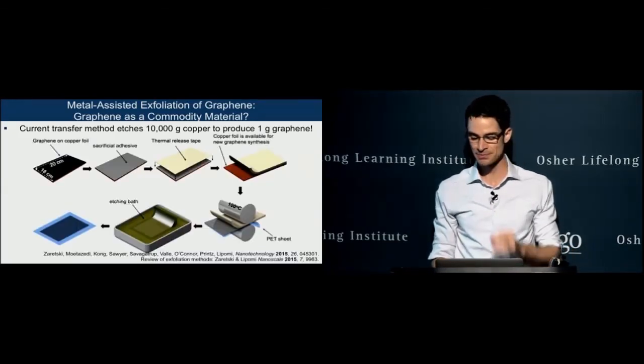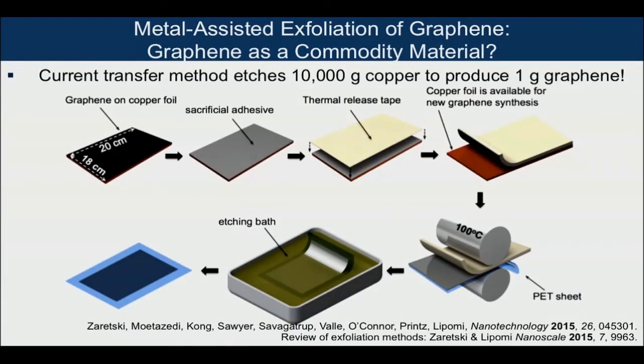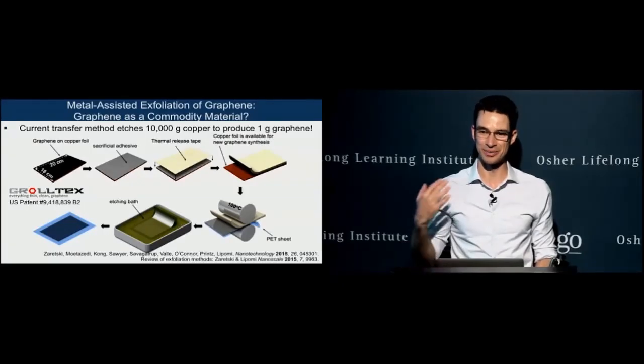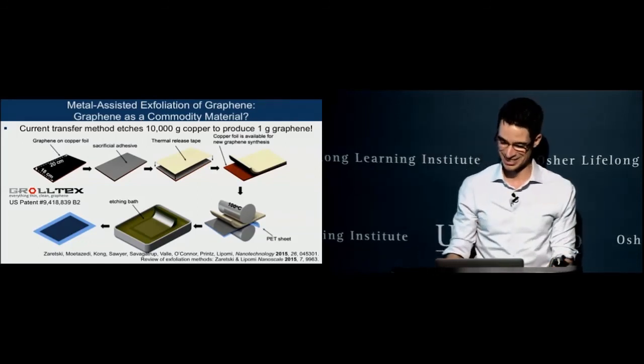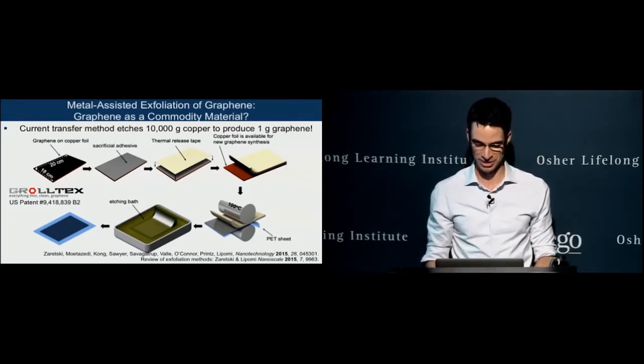Now ironically, we call the copper a catalyst, but it's really much more than a catalyst, and it's not a very green process. So my student came up with this method, and the basic idea here is that you can strip the graphene off the copper while leaving the copper safe for another cycle of growth. Now it took a long time to be able to figure out how to strip the graphene off because copper and graphene hold on to each other really tightly. But what he did is we patented this, and he started a company which is now based in Scripps Ranch, and he and his business partner raised a $1 million Series A financing round, and actually they sold their first product last week, and my research laboratory was their first customer. So that might be a conflict of interest, but I'm pretty sure the lawyer said it was okay.